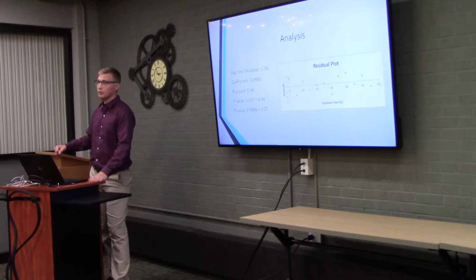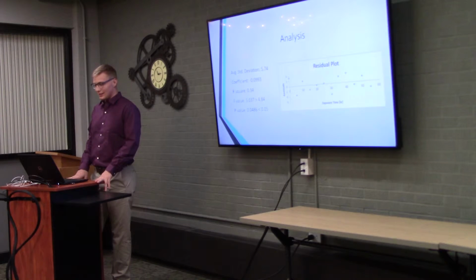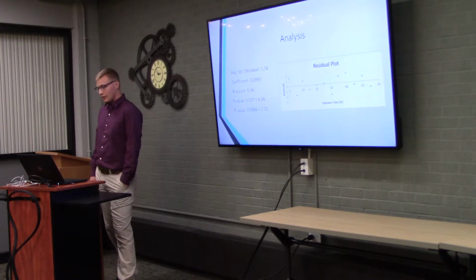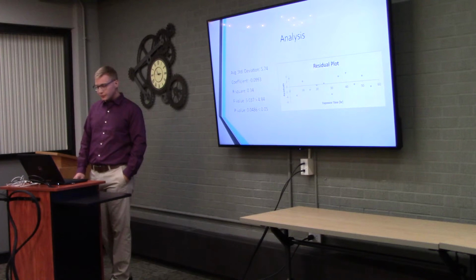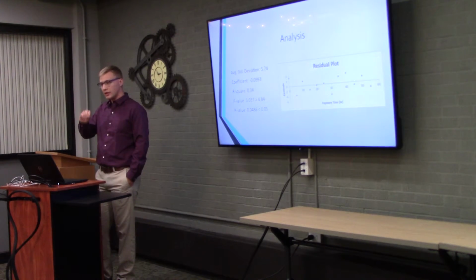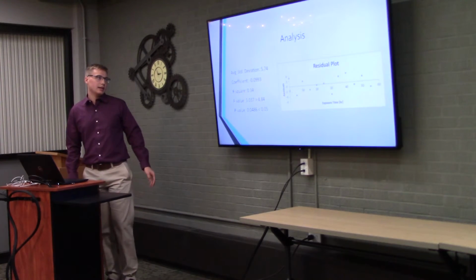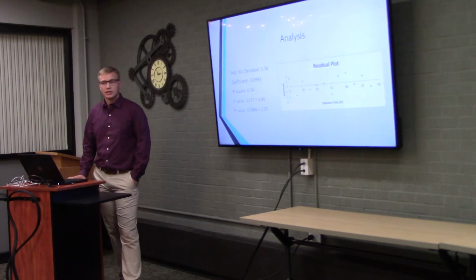And the F value and the P value, long story short, essentially means that in a 90% confidence interval, this coefficient is statistically significant. So we can be 90% sure that the hardness of the Hastelloy N decreased at a rate of 0.0993 per hour on the Rockwell hardness scale. And this residual plot right here, I put that there to show how well the linear relationship fits with the data. You can see that it's a relatively random and equal distribution of residuals on either side of the line, which essentially means that the linear trend line is the correct fit for the data.